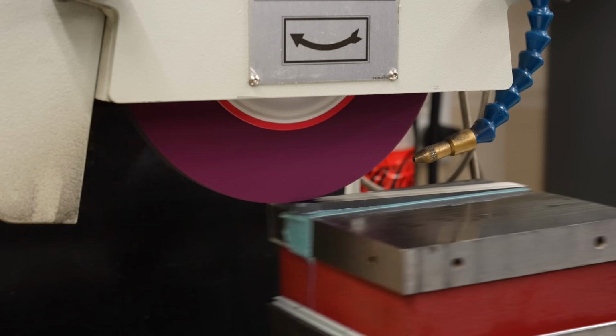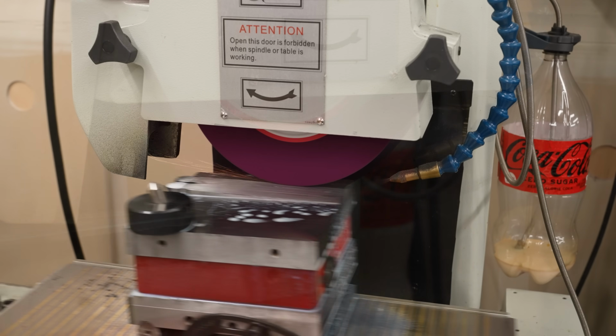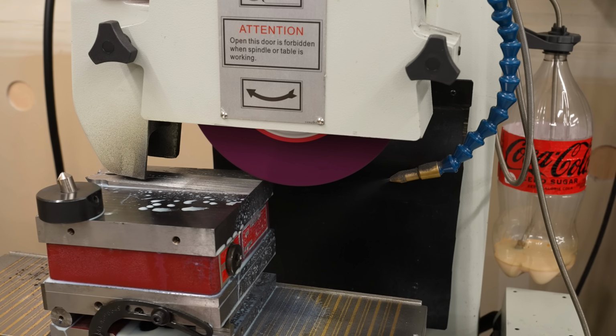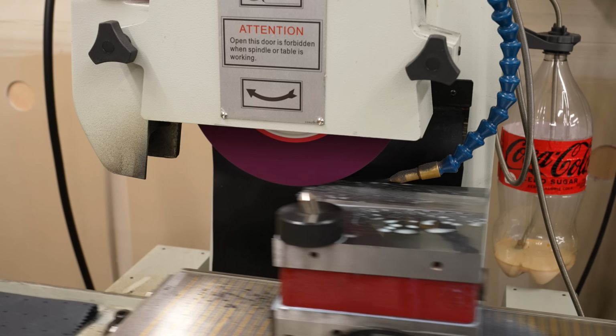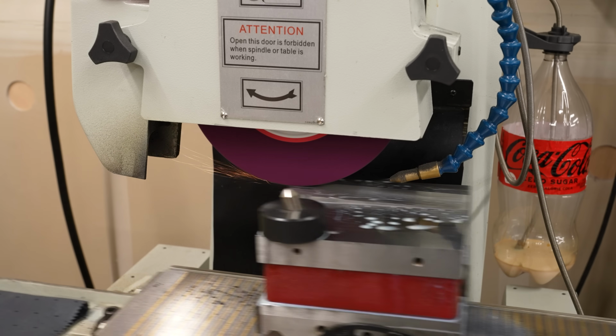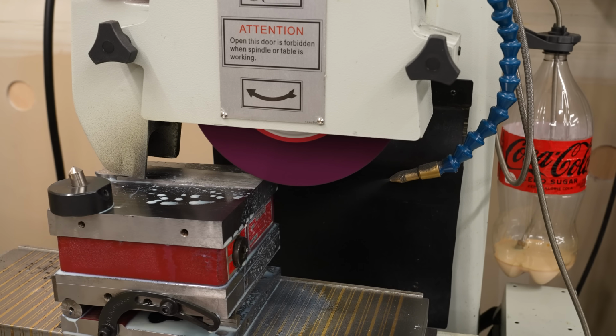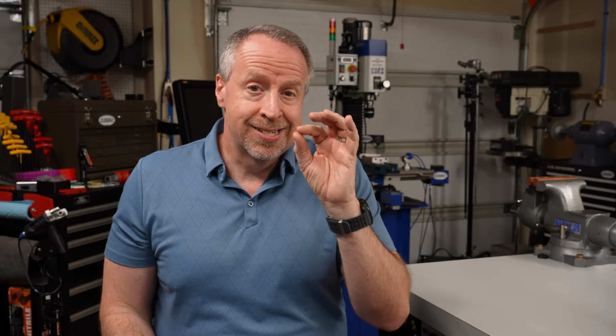And then with one side cleaned up and flat, I can flip it over, placing the now flat side down on the mag chuck and grind directly to dimension. Now I say that like it's easy, but it's complicated. I only have mist coolant on this grinder, and it is easy to build up heat in the part. The slightest bit of heat in a thin part like this causes it to warp, causes the thin tip to lift up off the chuck and bite into the wheel.